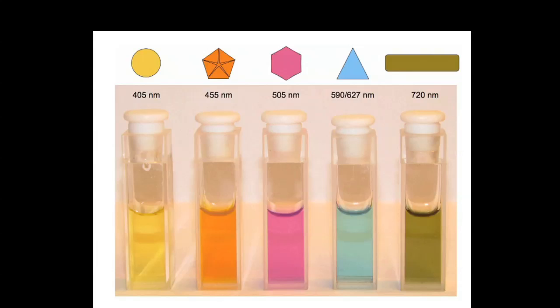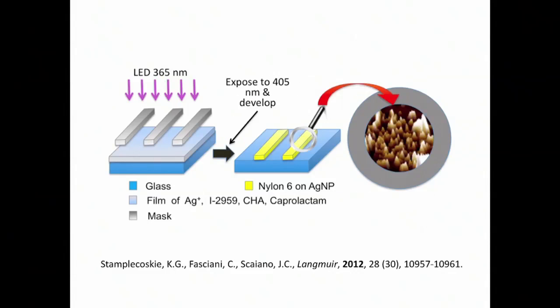Following this original research, we gained some expertise in making nanoparticles of different metals with different shapes and different optical densities. We now focus more on using these particles in novel applications. For example, the computer chip fabrication industry faces a dilemma that there is a need to generate smaller lithographic features. This is Moore's law, but current technology is reaching fundamental limits related with the diffraction limit of light. We think that the best way to beat this diffraction limit is to not be diffraction limited. In a couple of recent works, we have shown how the enhanced electromagnetic field around plasmon-excited metal nanoparticles can be used to generate polymer features that are 20 times below the diffraction limit. The extreme heat released at the surface of nanoparticles by plasmon-excitation can be used to do the same.